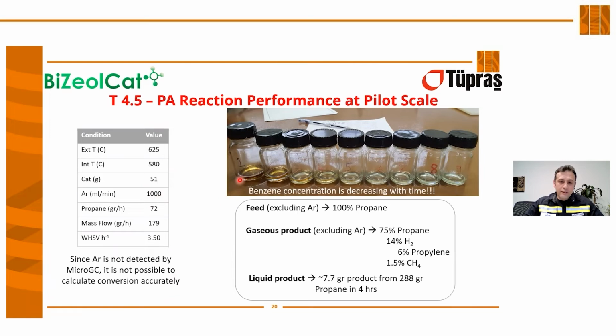We obtained liquids in each hour, as you see in this picture, and the product color is dark brown. During the course of the reaction, after 5 to 6 hours, the color becomes transparent. We understand that the benzene concentration in the initial phase of the reaction is higher than in the final phase.